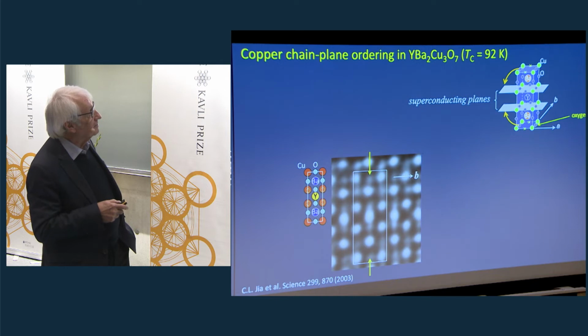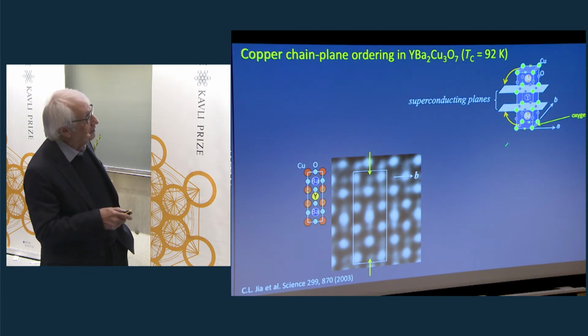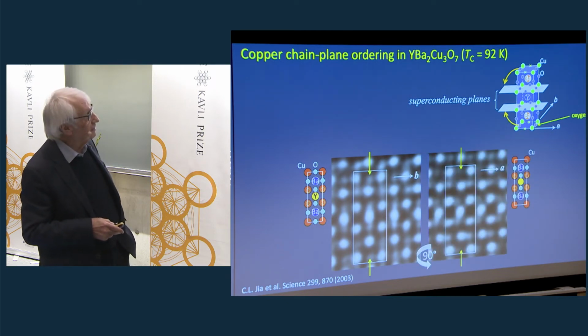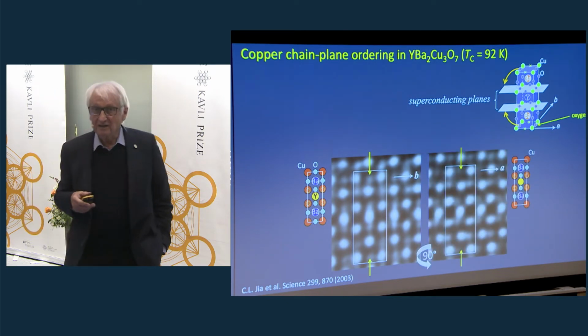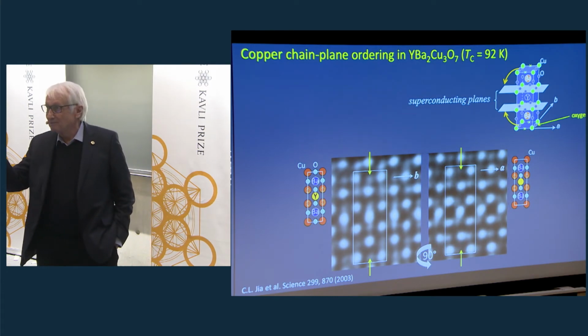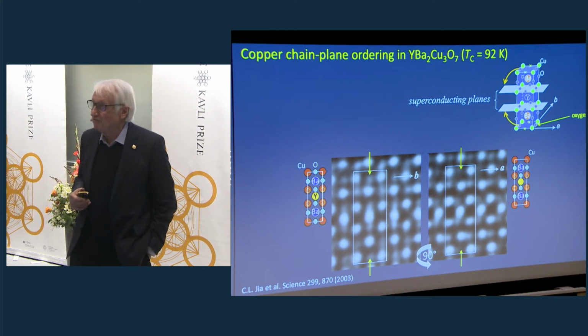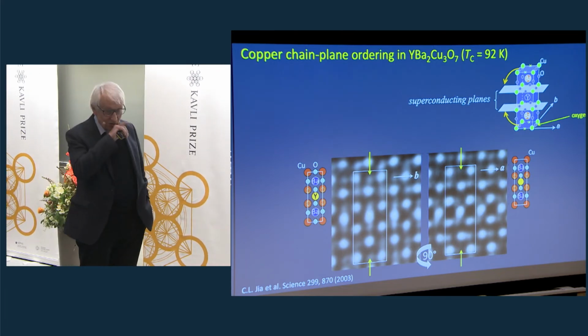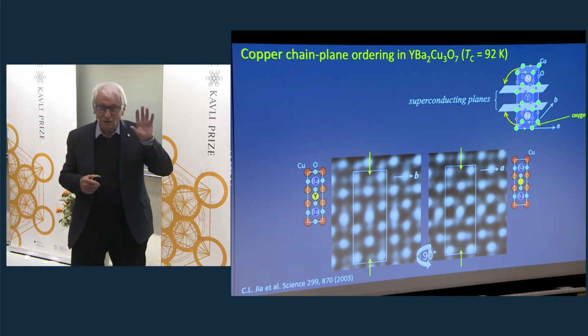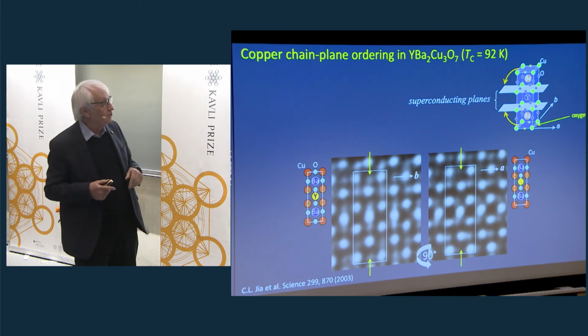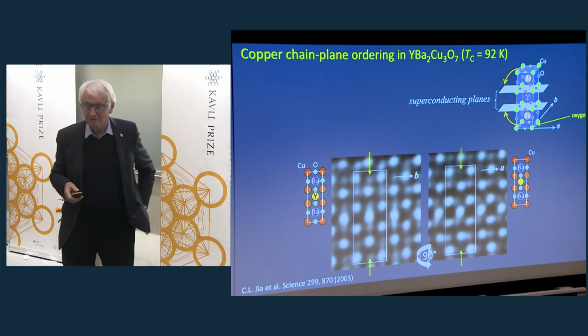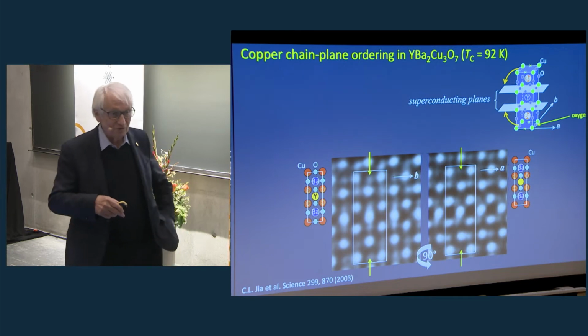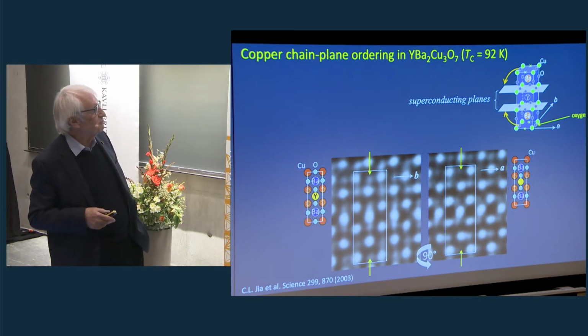Here we have the copper atoms, here we have the barium atom, and we see the oxygen here, down here and up here. So we are looking from this direction, so we see the oxygen. And now we tilt the sample by 90 degrees in the microscope, which those who do this know is not trivial, because you also have to align your atomic rows perfectly and so on. So such an experiment is not easy to perform. So this is one of those which worked.